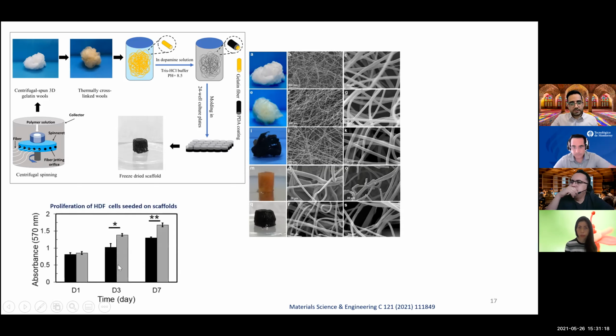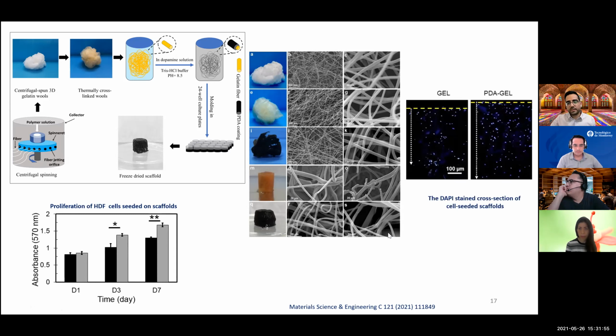The other thing is that we did proliferation of the HDF cells on the surface of those scaffolds. And as you can see here, after 7 days, we have a significant increase in the amount of the cells. The black one is related to the pure gelatin, and the gray one is related to the gelatin containing a polydopamine coating. And as you can see here, the samples containing a polydopamine coating have a significant increase in the amount of cells. The other thing that is really interesting is regarding the histological properties, and it's the DAPI staining cross-section of the cell-loaded scaffold, because we wanted to know how much those cells can penetrate, can infiltrate the final scaffold.